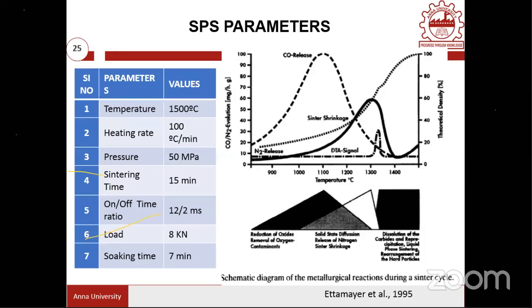Once you have more than 1200 degrees centigrade, solid state diffusion begins. As a result, the nitrogen release will be removed, and a dissolution-precipitation mechanism will also be triggered at high temperature. Therefore, the carbon monoxide emission as well as the nitrogen emission will stop. So if we take a temperature close to 1400 or 1500 degrees centigrade, there is no nitrogen removal or carbon monoxide removal, and you will get full densification. The sintering is 100%. That means it is full densification. You can achieve close to theoretical density. Therefore, looking at these aspects, we have proposed this value.